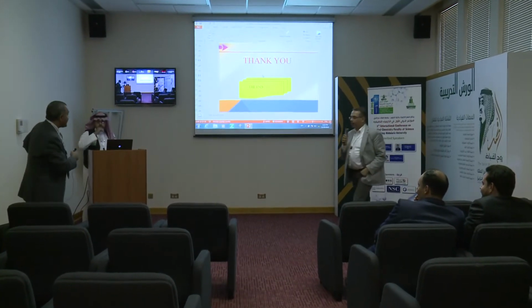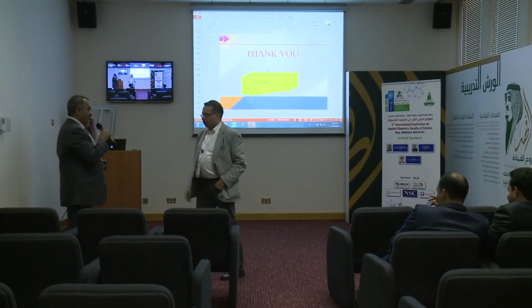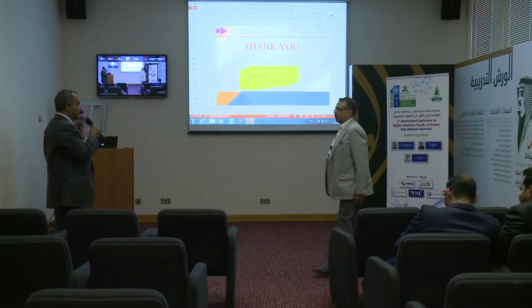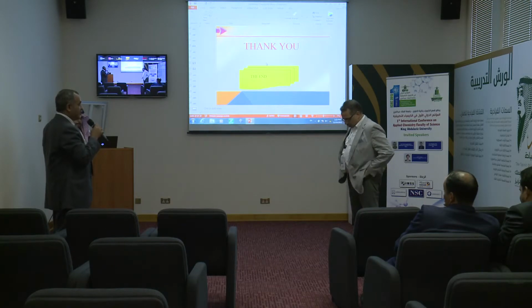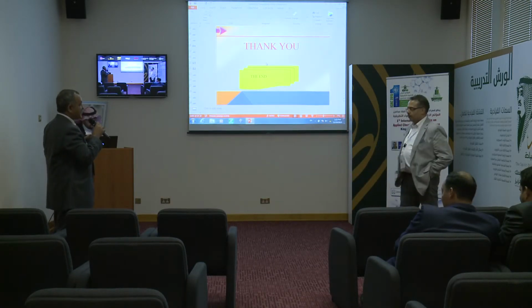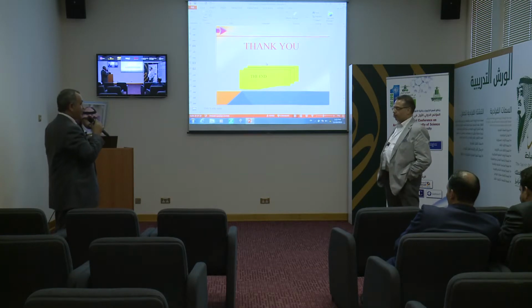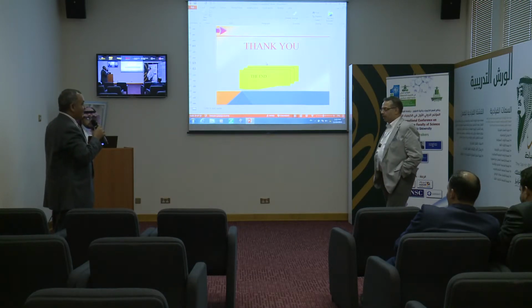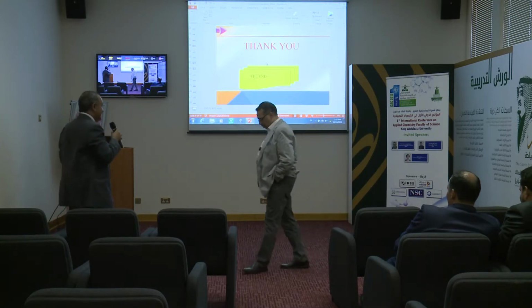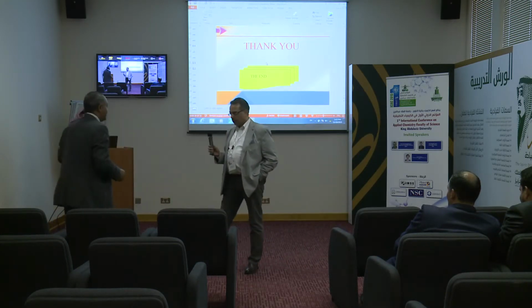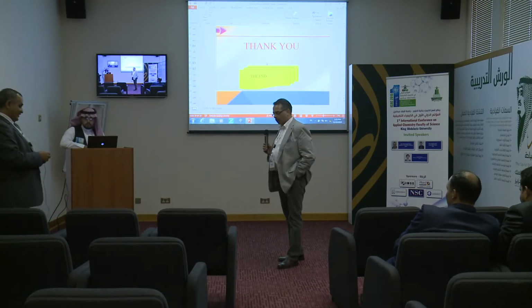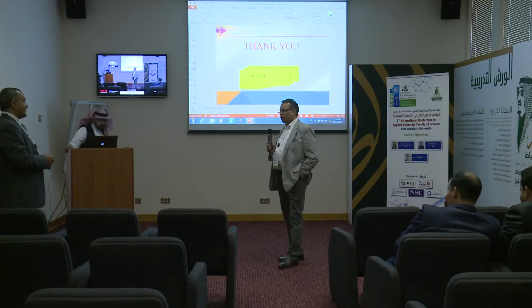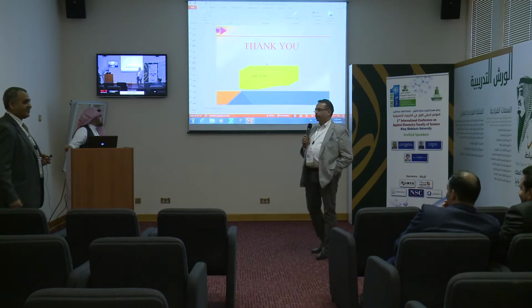Okay, please. Regarding the active sites, you are working on manganese and cobalt mixed oxides. So, what's the real active site? Is it cobalt 2, cobalt 3, or is it manganese 2 or manganese 4, or is it cobalt 4 or manganese 2, cobalt 3? Do you have any idea about this? Yes, all of them are active sites, but the most active site for this catalytic reaction is manganese. So the presence or the absence of manganese species has much effect on the catalytic activity.